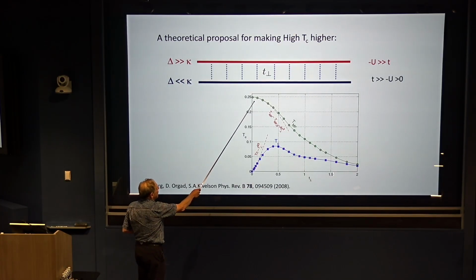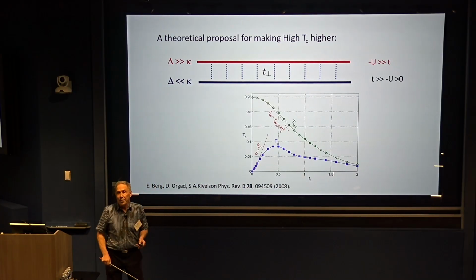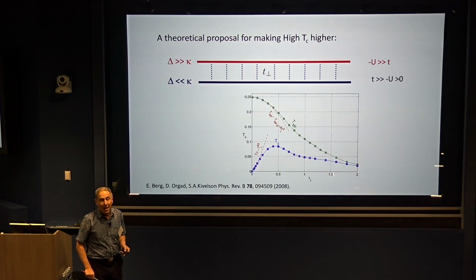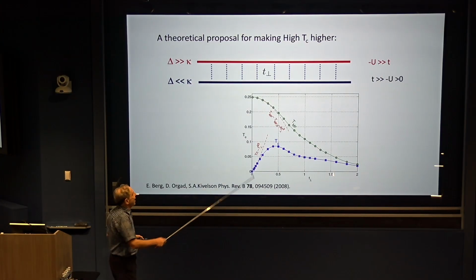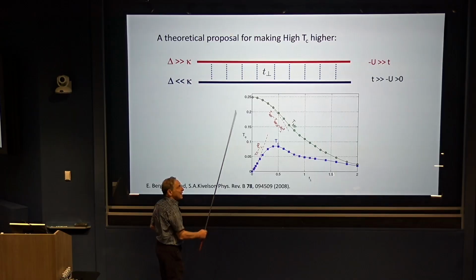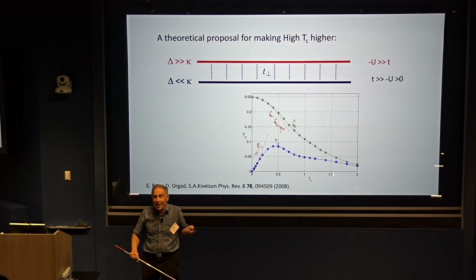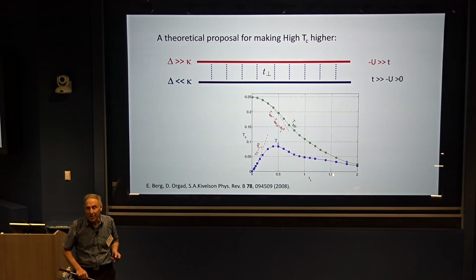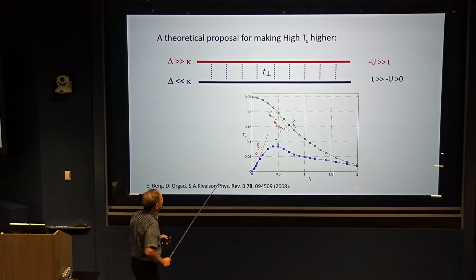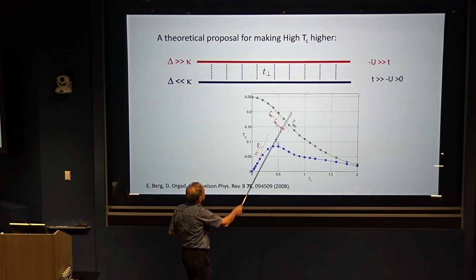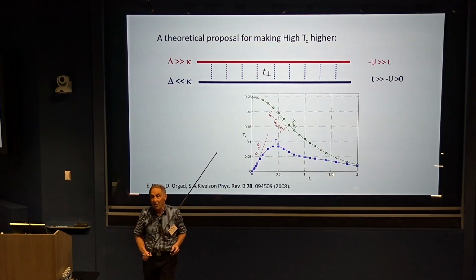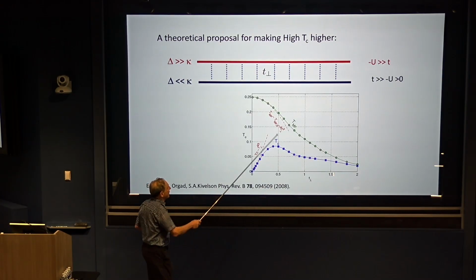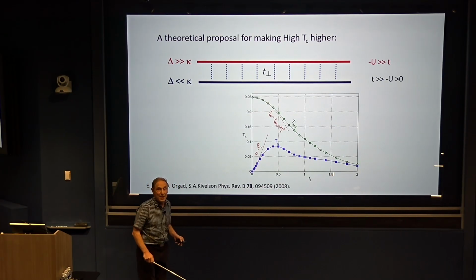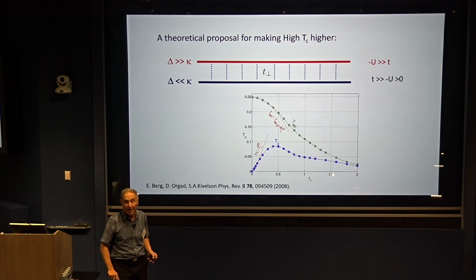We calculate the mean field TC, and that drops as you turn up T perpendicular. And that's the inverse proximity effect. The BCS mean field theory on this negative U sites gives you a perfectly good TC on the order of U. And then as the electrons spend less and less time on the layer with the attractive interaction, the mean field TC drops monotonically with T perpendicular.